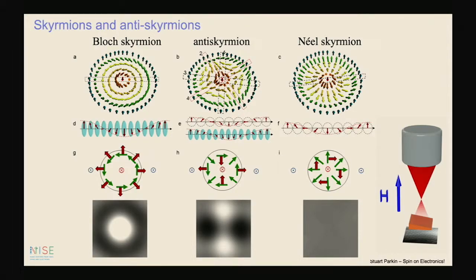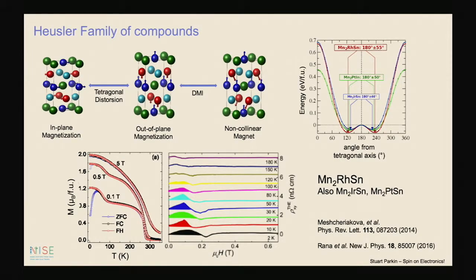The Bloch skyrmion you can see on this side looks like a white blob, a region of increased electron intensity in the middle of this blob. And that's what's been seen first by Tokura and his group at RIKEN, in iron germanium at room temperature. And the anti-skyrmion we calculated should look like this. You see two lobes of increased intensity of the electron beam and two lobes of decreased intensity, like a cloverleaf structure. And this is what we were able to see in a material that Claudia discussed this morning, these